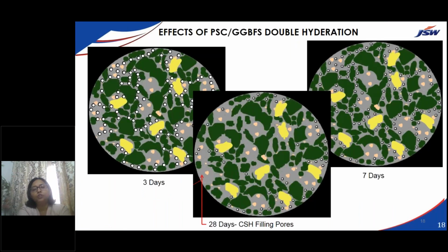So we would like to just show you the pores and gel. When you see here at 28 days, the pores and gel have become smaller; in 3 days, they were very big. With the hydration products of the slag coming in, the pores and gels become smaller, and the durability of the structure increases. The permeability of the structure reduces.